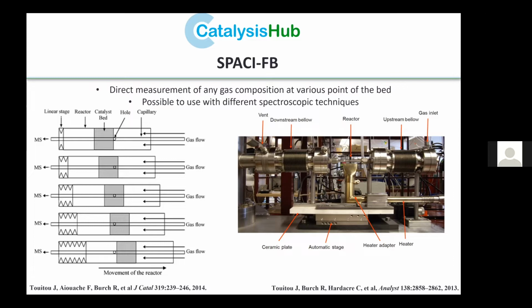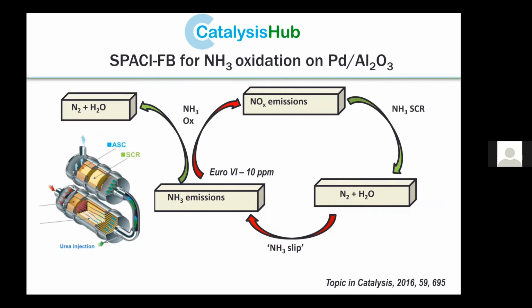This technique uses a capillary which has been bored through by lasers, and this capillary is embedded in the catalyst bed. Rather than moving the capillary, because it's very fragile, we move the catalyst bed. The capillary is connected to a mass spectrometer at the end, where the mass spectrometry data are collected. We apply this technique to ammonia oxidation.